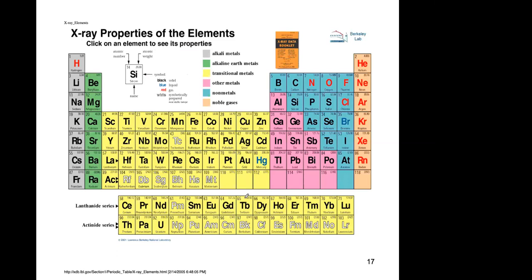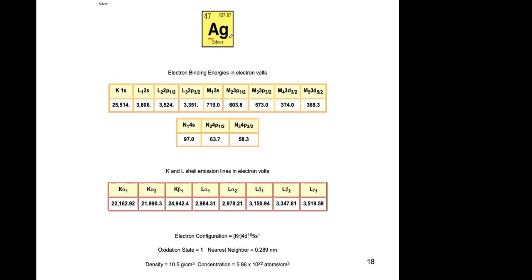I included this booklet that you can download from Berkeley Lab. You can get the periodic table, and you can click on an element. For example, here is silver, and it will give you the binding energy of all the electron levels. For example, for K, the 1s level, it is 25,514 electron volts, which is quite high. And a more external level, N3 or 4p3/2, is 58 electron volts.